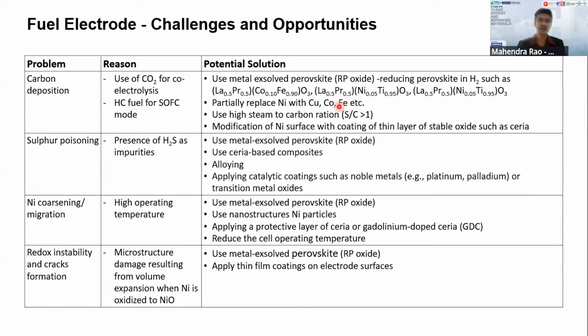And some of the potential solutions that many researchers presented in many papers: the new method that people are currently considering is to use metal exsolution perovskite-based materials to mitigate this issue. And then there is another solution that is already known, where we use bimetallic electrodes by partially replacing the nickel with copper, cobalt, or some other metal to reduce the carbon deposition. And in terms of operation, using a high steam to carbon ratio is also a potential solution to mitigate the carbon deposition. And then in some of the works, they also modify the nickel surface with stable oxide layers such as ceria to reduce the carbon deposition.